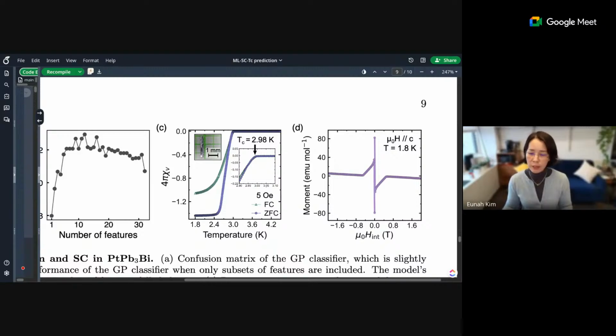My collaborator, Leslie, was able to quickly synthesize the material because its structure was already known and it is known to form. It just had not been tested for superconductivity. So she synthesized the material. Here is a picture of the crystal. And then they measured. Here you can see from the zero field cooled susceptibility measurement that the identified Tc is 2.98 Kelvin. The GPTc prediction was 2.93. It didn't involve calculations. It just required a chemical formula and a structure.